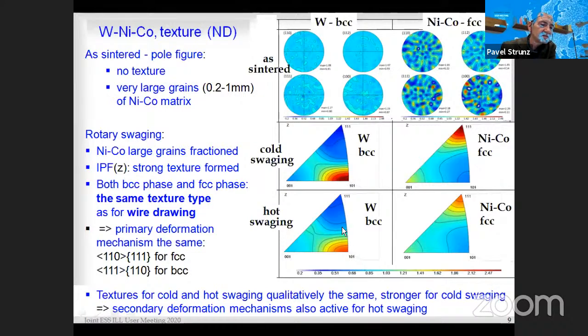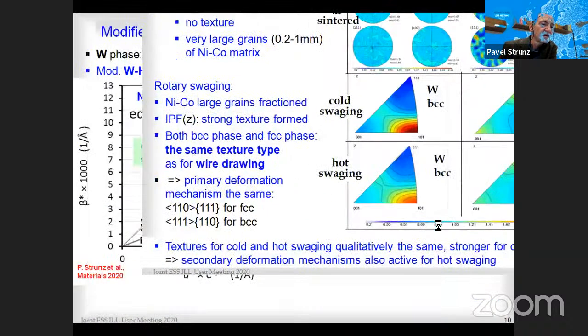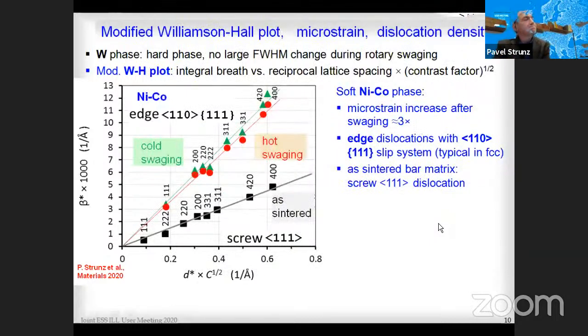The second thing is that you can see that qualitatively the same texture is for cold swaging and for hot swaging, but in the second case, for hot swaging, there is smaller texture. That means in this case, there was most probably active also a secondary deformation mechanism. Now back to the peak broadening. Here is a modified Williamson-Hall plot for the matrix phase. We can see that in the soft nickel cobalt phase, the microstrain increased after swaging three times.